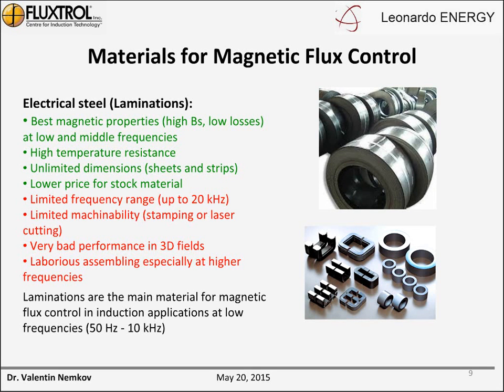It's a limited frequency range. Typically we say that it's 20 kilohertz, but sometimes with good cooling and so on, it could be used even at higher frequency. But thickness of laminations should be smaller when we go to higher frequencies.